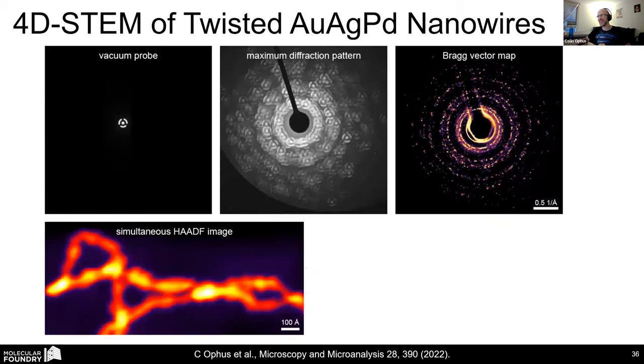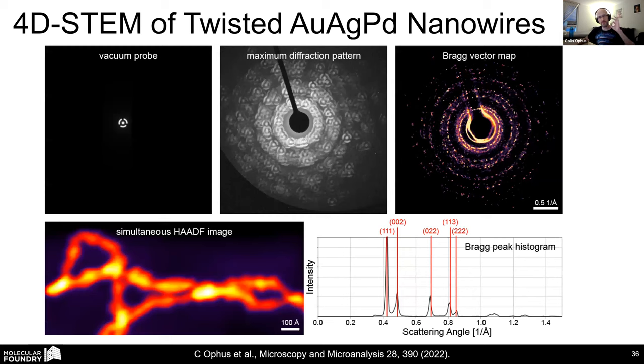And so maybe one last note, I will say there's no free lunch. These bullseye probes make the probe tails larger, so you lose spatial resolution if you stamp an amplitude pattern into the probe. So I guess my answer, Bob, would be it's complicated. Right. And I was thinking more about the probe size rather than the convergence angle, but of course that's another variable. Oh yeah, they're reciprocally related, right? So larger semi-convergence angle, smaller probe size.